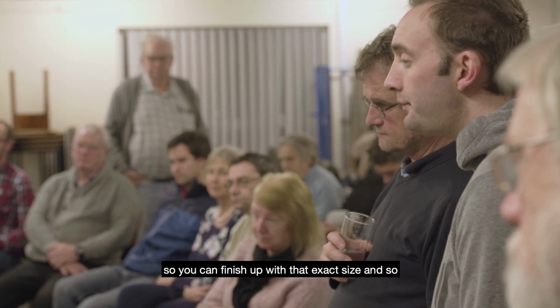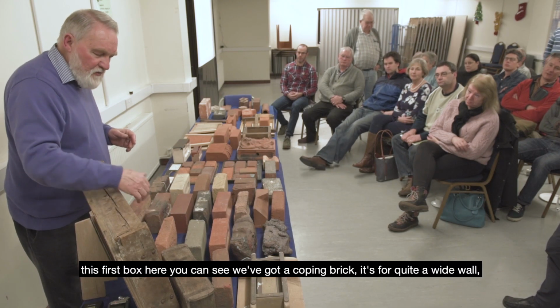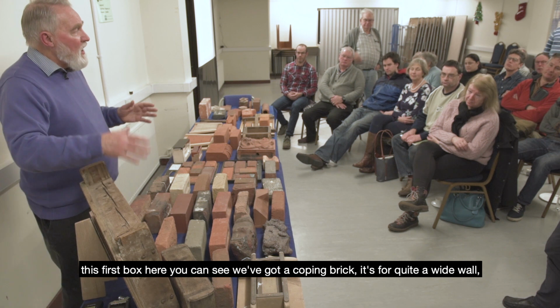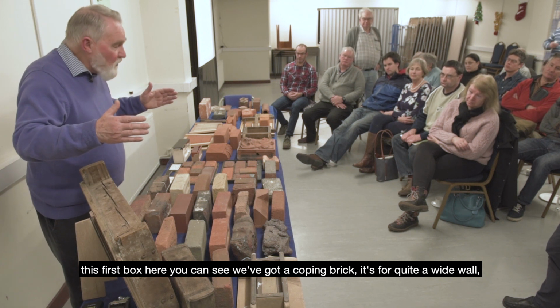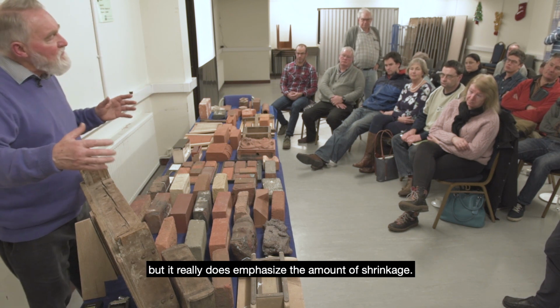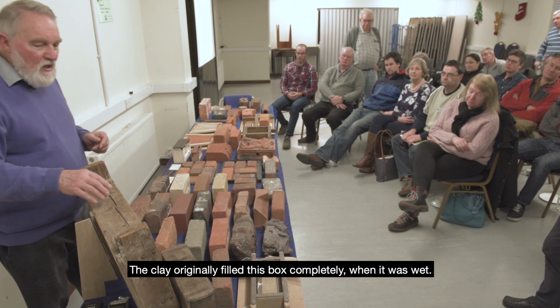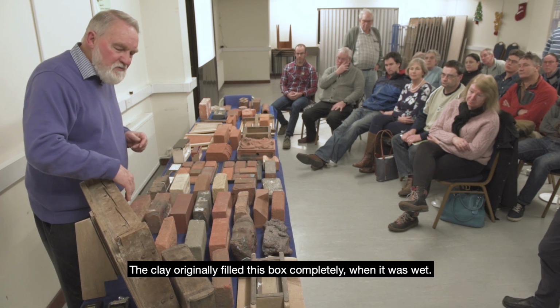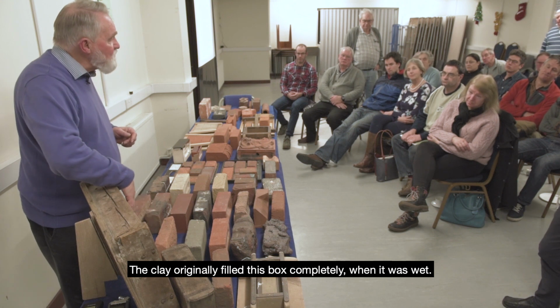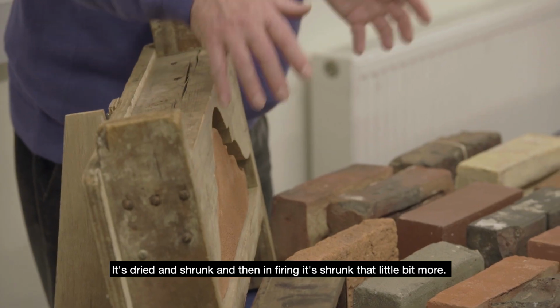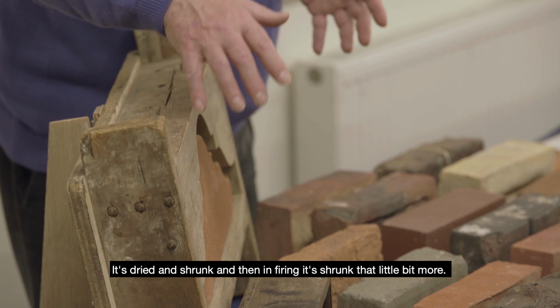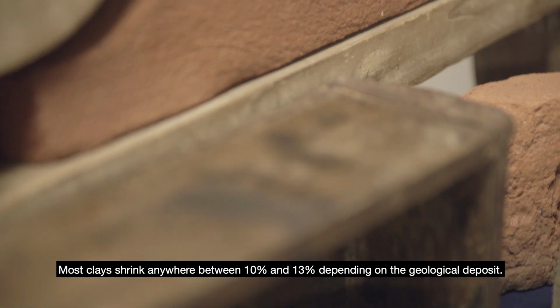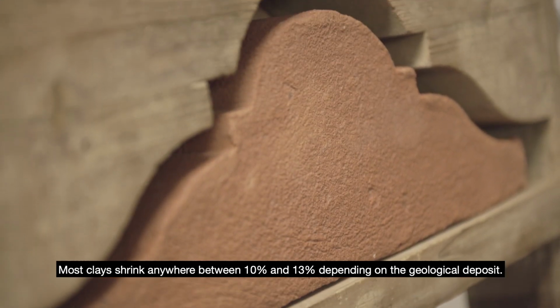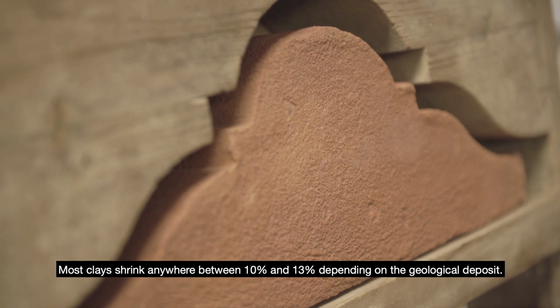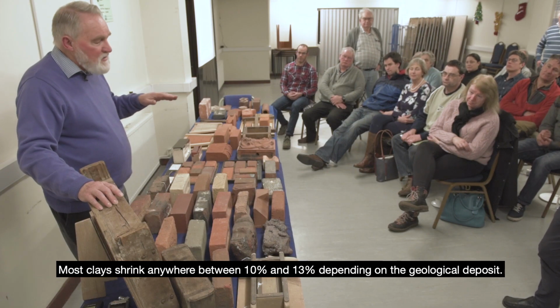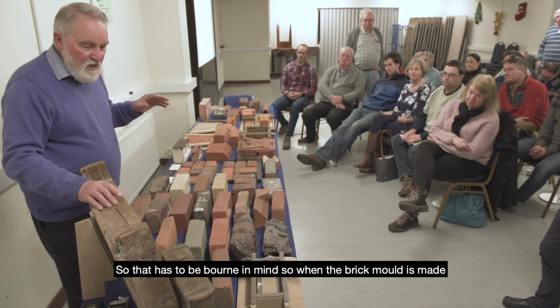And so this first box here, you can see we've got a coping brick. It's for quite a wide wall, but it really does emphasize the amount of shrinkage. The clay originally filled this box completely when it was wet. It's dried and shrunk, and then in firing it shrunk that little bit more. Most clays shrink anywhere between 10 and 13%, depending on the geological deposit. So that has to be borne in mind.